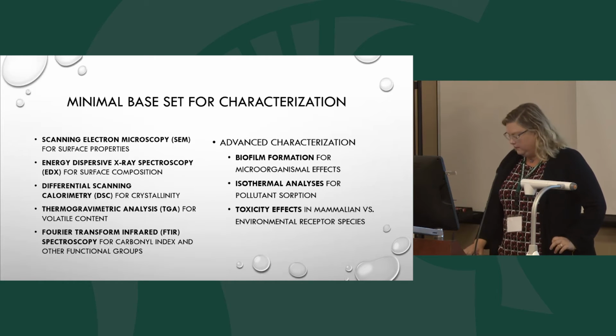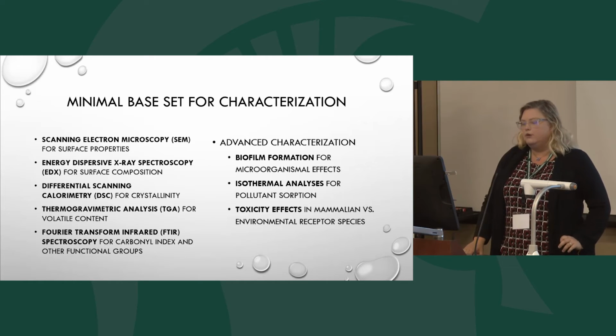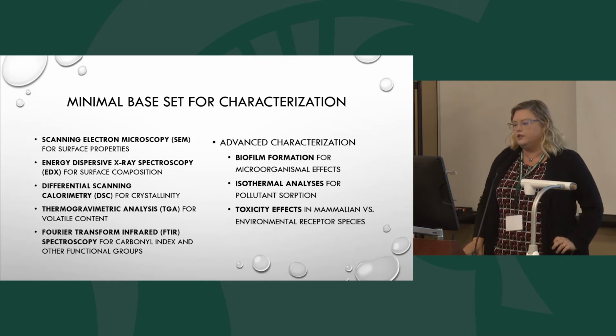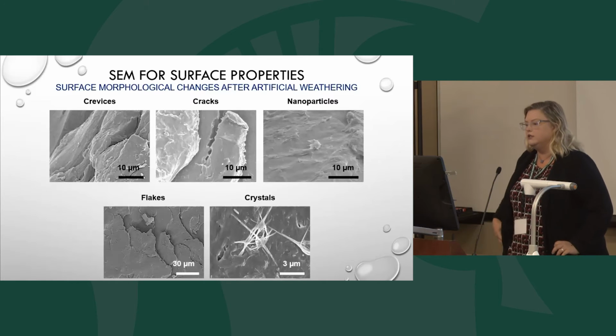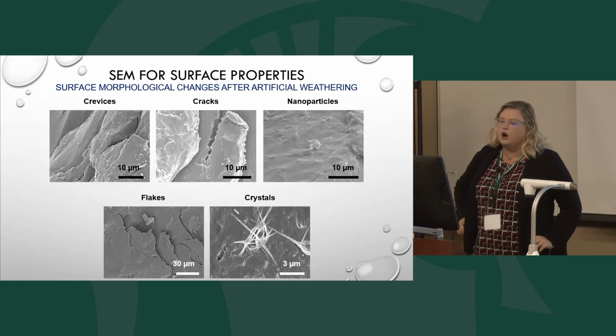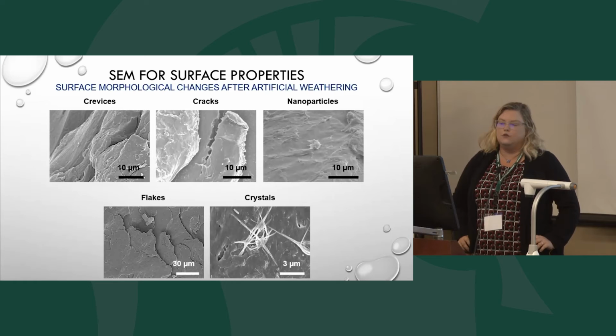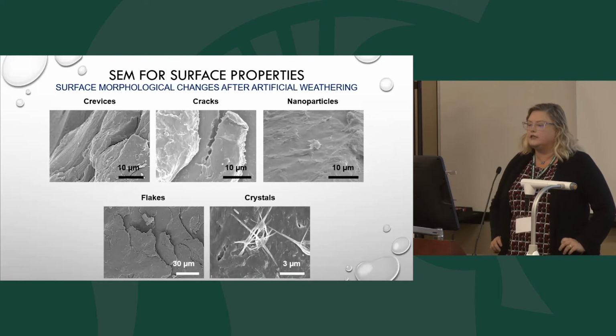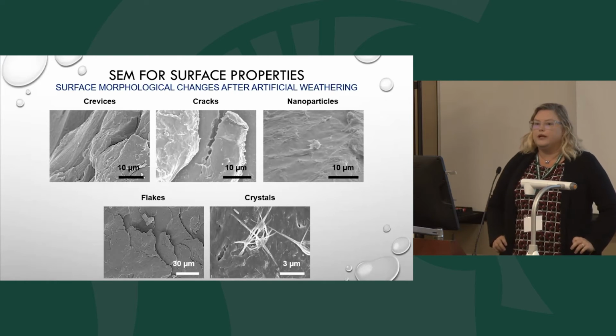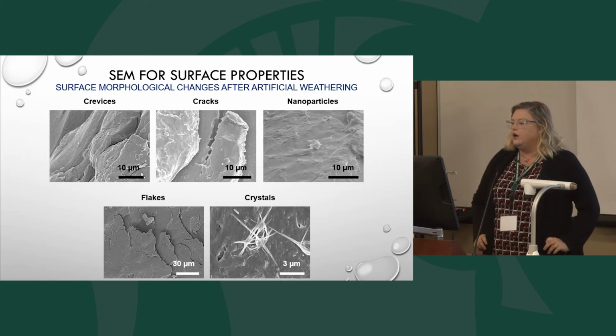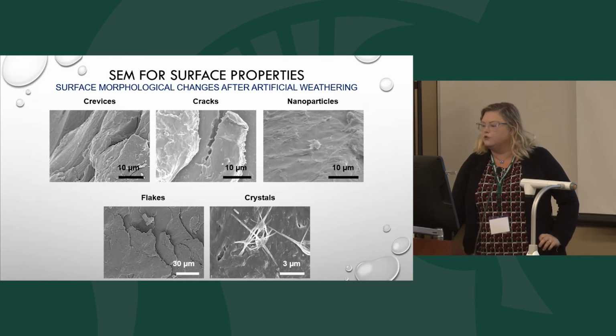And of course, toxicity effects, which we've started going into, but it's very difficult and we're just not ready to start doing some toxicology ourselves. What we are noticing after artificial weathering is a huge increase in the amount of cracks and crevices in the microplastic surfaces. We also see nanoparticles form.